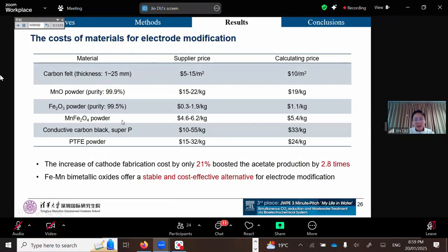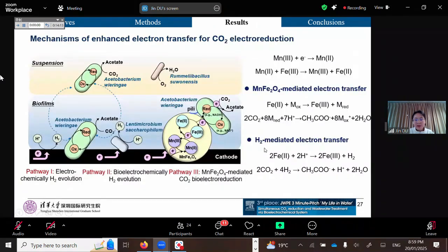In terms of economic feasibility, the manganese ferrite modification increased the electrode manufacturing cost by only 21%, yet boosted the acetate production rate by 2.8 times, demonstrating it as a simple and cost-effective modification strategy. Based on the above results, we propose a mechanism for the role of manganese ferrite in the MES system. The redox pairs of the manganese and iron work synergistically to promote the cathode and microorganisms electron transfer, thereby accelerating CO2 reduction to acetate.